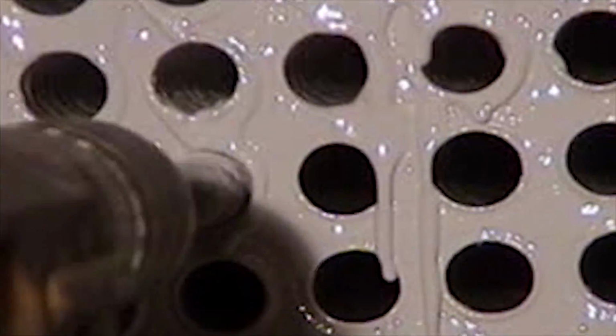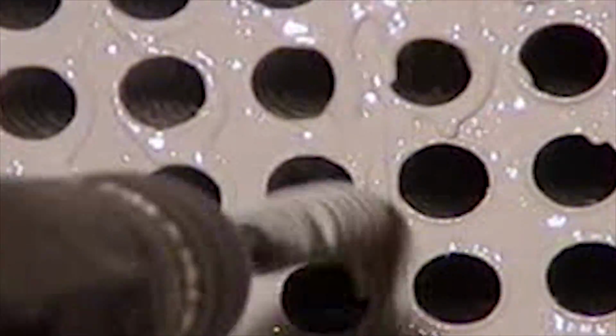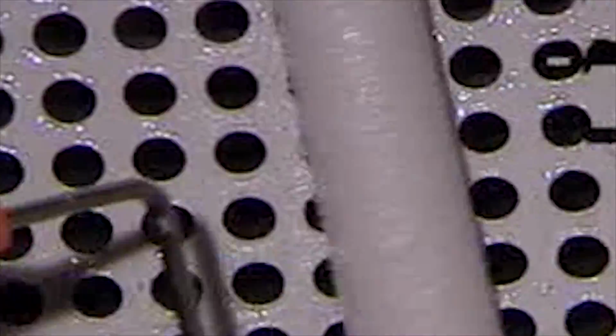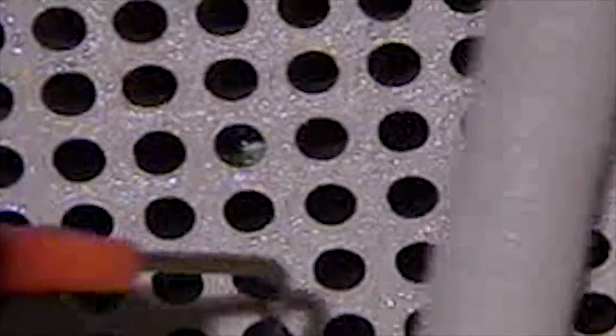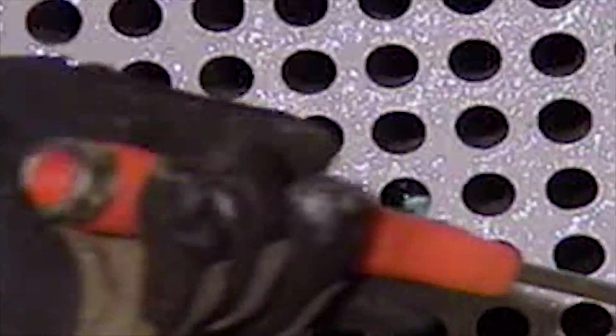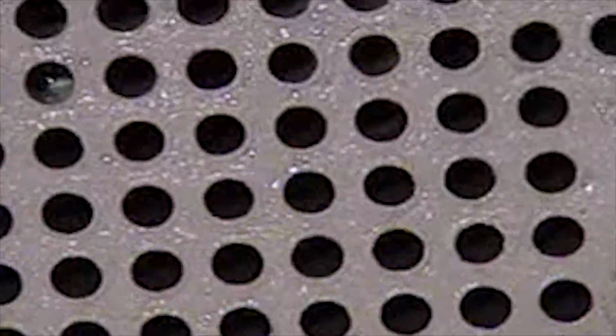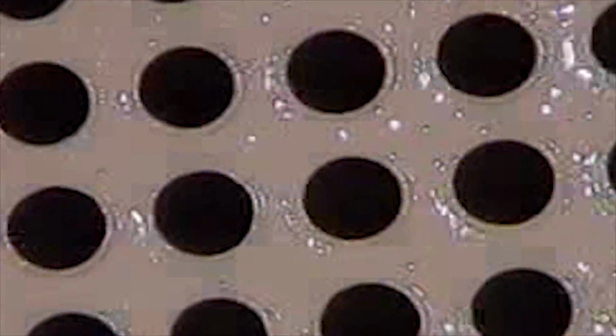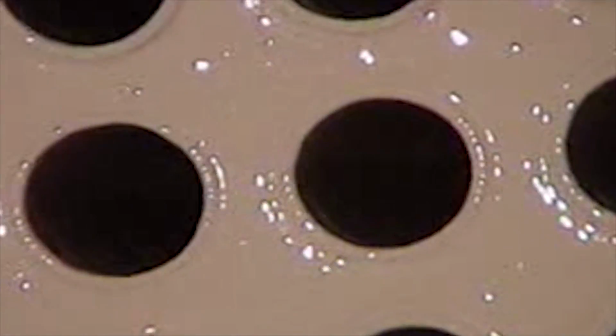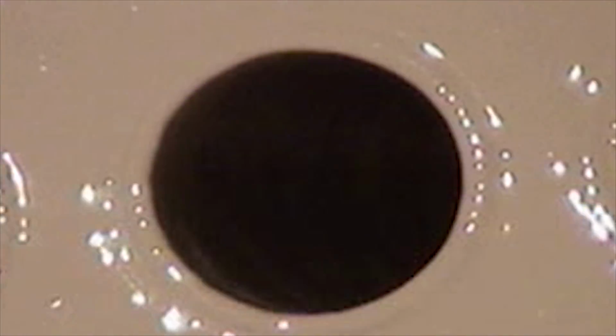And again, we pass several times down each tube to smooth the material and work it in sufficiently. Between each coat, we use a 1/4 to 3/8 snap dry roller to smooth out the coating, and this results in a smooth finish on the tube sheet face. After 3 coats down the tubes, we end up with approximately a 30 mil finish coat. If you desire a thicker finish, you can roll additional coats over.